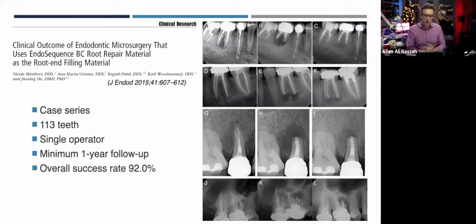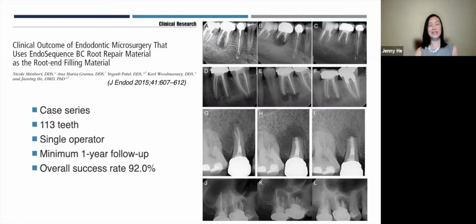So Dr. He, what about surgery? Time to look at a few studies. So we have a few more studies on the root repair material compared to the studies we have on BC. So 2 of these studies came out of our group. The first one was based on cases treated in our practice. So this was also a retrospective case series with over 100 teeth, mostly posterior teeth. And we found that when we use root repair material as the root end filling material, we're able to get a success rate of 92%.